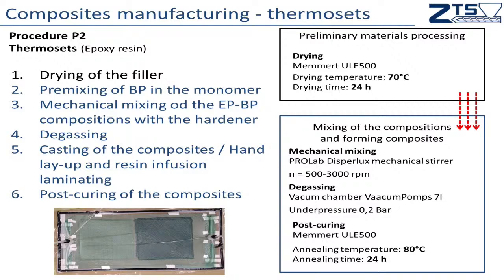Now we can move to another slide, and we'll see that the creation of the epoxy composites is also almost the same as in industrial conditions. We didn't use any sonification method or the mixers that are typical for laboratory scale. We use a big mechanical mixer with high rotational speed. All compositions were degassed, and then we prepare the composites by the casting procedure, as well as hand layup or resin infusion procedure.